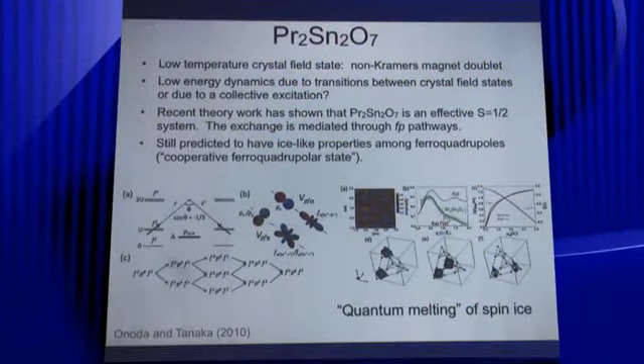So Onoda-san, after we published our results, started discussing what really happens in praseodymium stannate. So we're happy to see this paper appear. There are some issues still in praseodymium stannate. The low temperature crystal field states, it's a non-Kramers magnetic doublet. We've been criticized that perhaps we have excitations between low-lying crystal fields, and that's what we're seeing in our spin excitations. But they did some recent theory work on this, and they showed that it's an effective spin 1/2 system, and they did some complicated calculations to show how the exchange works in this compound.